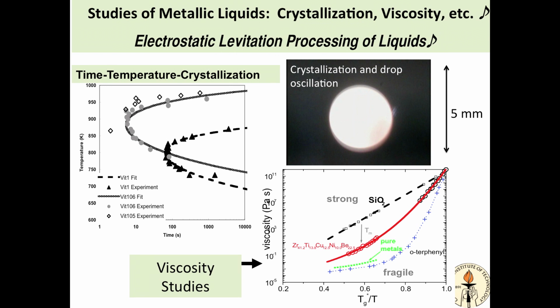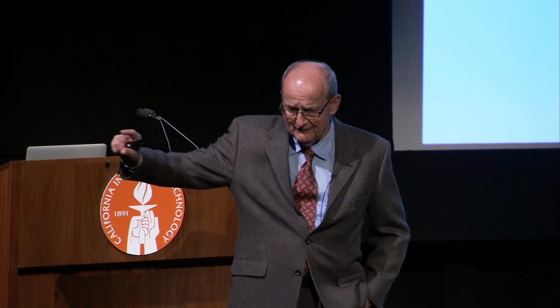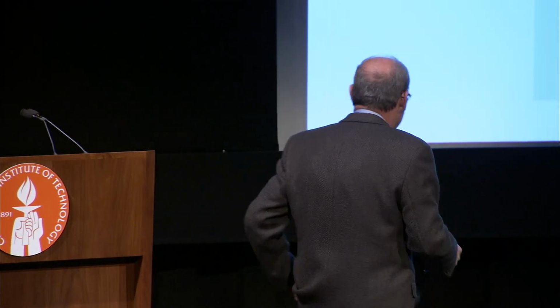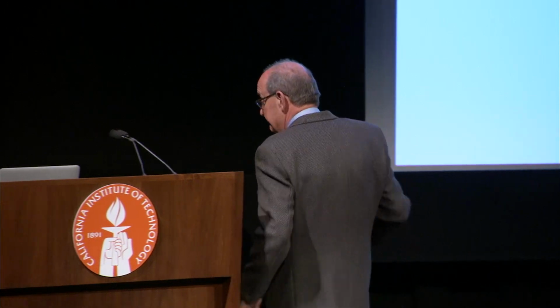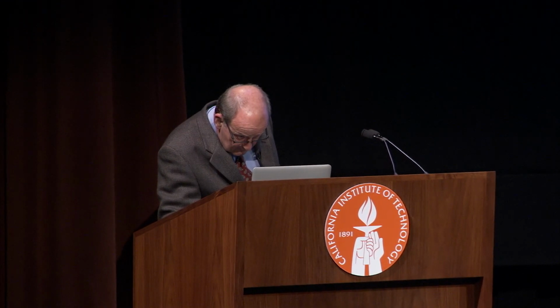And you can see it takes 10 seconds, for example, here. That's a different alloy. This one takes 10 seconds to nucleate crystals. And we can ping the drop, make it oscillate, and if you watch the damping of the drop oscillations, that tells you what the fluidity or the viscosity is. So you can do all this stuff and measure it. It's fun to look at a movie again.